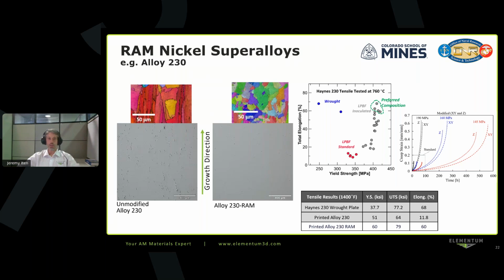So how do you solve these? Well, the RAM process is also suitable for solving this. You can see the EBSD colored image at the top of those microstructures. We've moved from that very highly textured oriented microstructure to a more randomly distributed, more equiaxed microstructure, and that's completely eliminated the micro cracking that would otherwise be present.